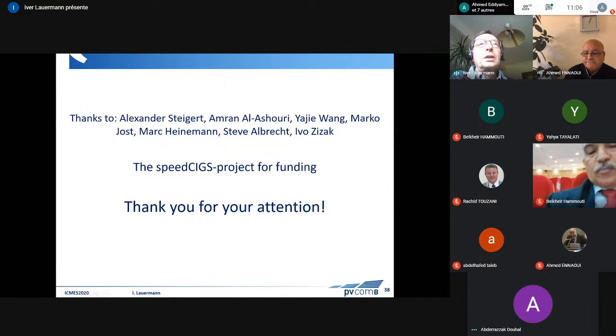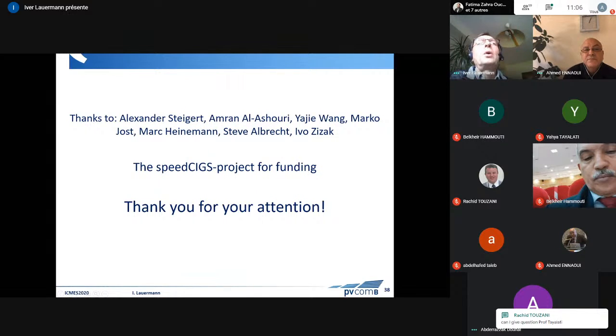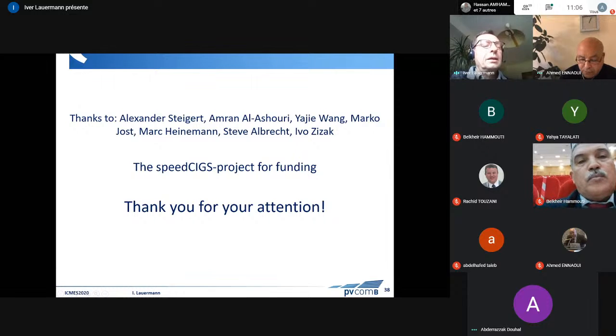slot die coating, and in the group of Bernd Stanowski at PVcomB, we are now also installing an evaporation tool for perovskites up to a size of 6 inch. So evaporation will be upscaled. This can be done fairly easily, but of course it depends again on vacuum, fairly expensive equipment.